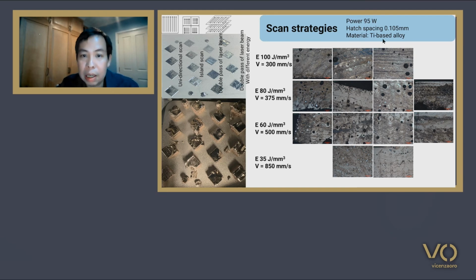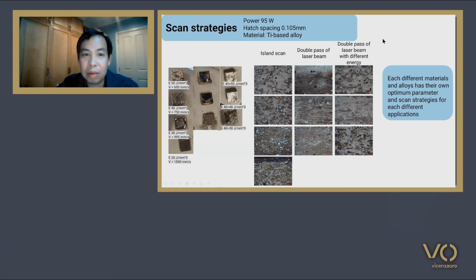And here, there are some more examples. You see here 40 plus 50. These are a double pass of the laser beam, and we found this technique to be working the best actually. So we must conclude though that each different materials and alloys have their own optimum parameters, and they have scan strategies for different applications. For us, the double pass is actually working the best.